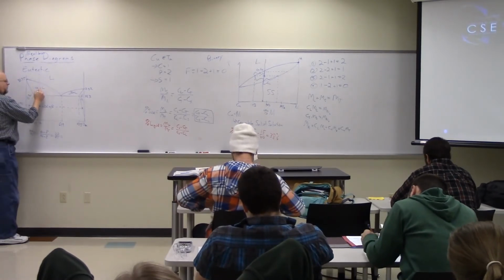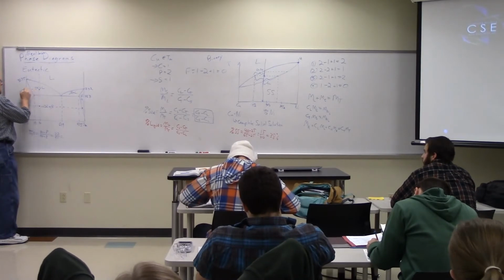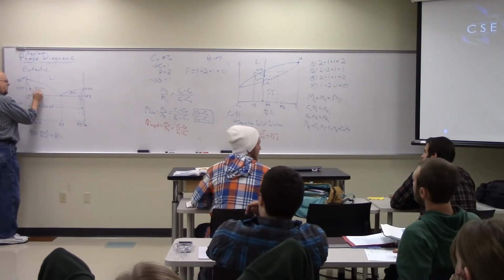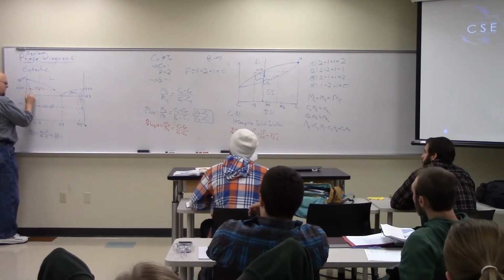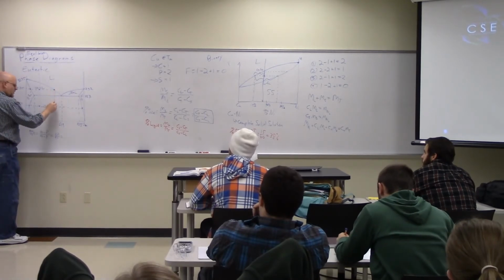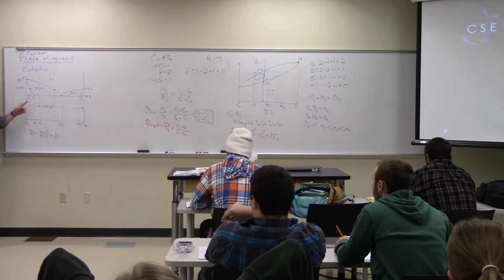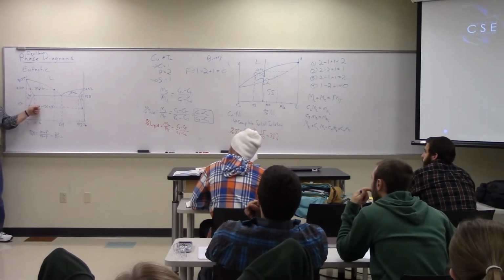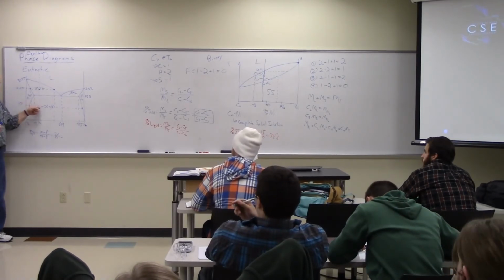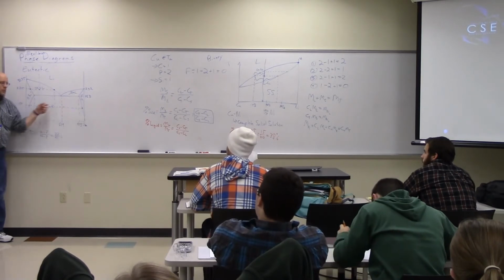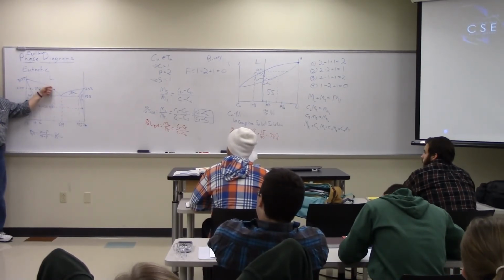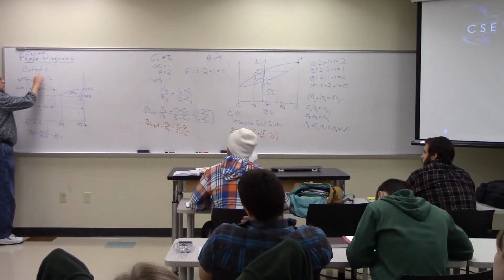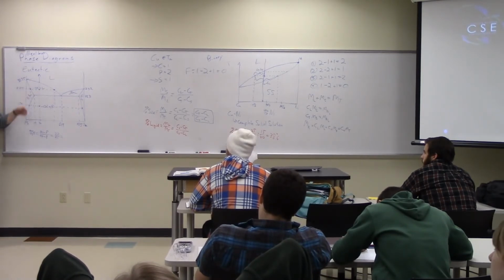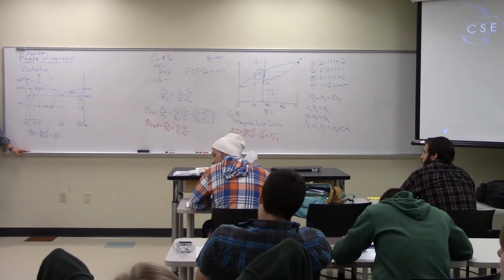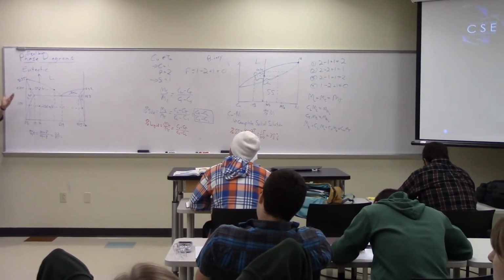If I'm at this point, at this temperature of, let's say, 220, these are the compositions of that liquid and alpha. The alpha is maybe 10% tin, and the liquid is maybe 50% tin. So in any two-phase region, the point where you're at, this composition at this temperature, doesn't actually exist. The only thing that exists there is a mixture of these two. If I warm it up, I get a mixture of these two. Only when I get to here do I actually get what it is, which is a 30% liquid. That liquid portion is a mixture of lead and tin, but because they're liquid, they're free to move around, so there's nothing to keep them in any place, so by definition, they're homogeneous.